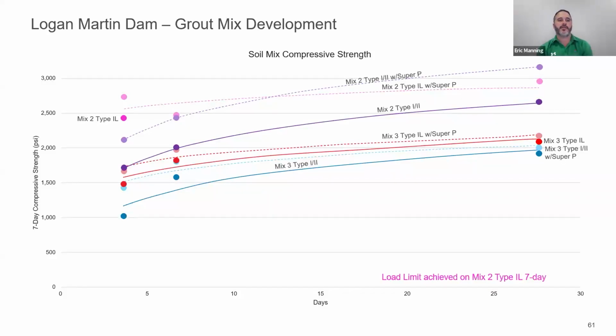That equated to roughly about 40% of the fly ash and cement content. So that means we replaced all the fly ash, and we were able to take some of the cement content and substitute it with the local clay material. We were able to achieve 1500 PSI, as you can see with this mix.